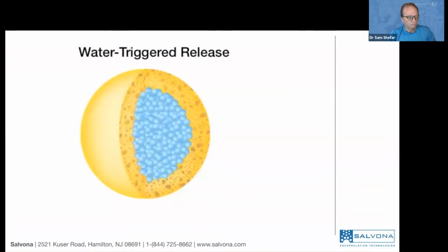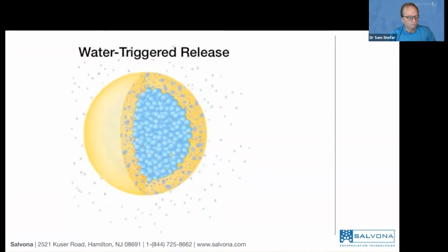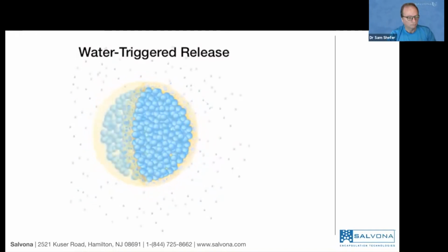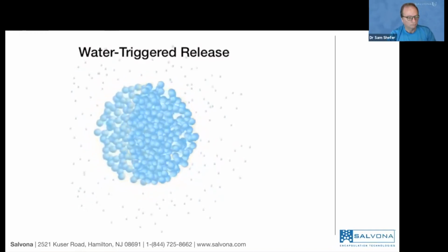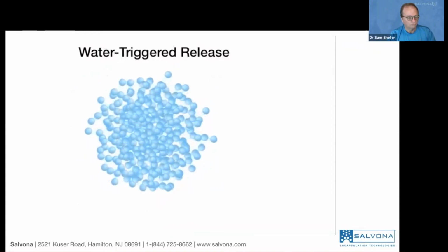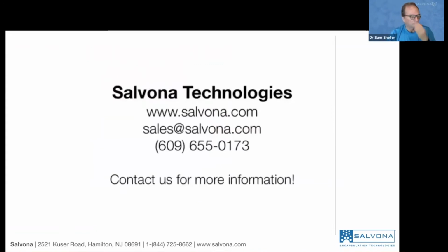Water-triggered release. MultiSal comes in a dry powder form that is stable until introduced to water. Upon contact with water, the sphere gradually absorbs the water and dissolves, activating the release of the submicron Sal spheres inside. The Sal spheres, in turn, break down and release the active ingredients. Salvona Technologies offers quality delivery systems that modify the way functional and active.